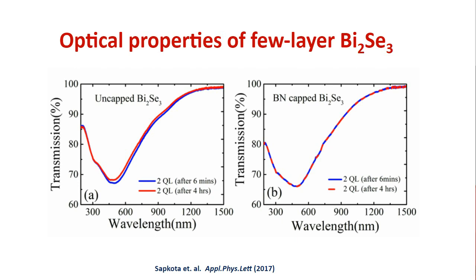In the capped sample, there is virtually no change, and that is exactly the result we wanted to see. That means if we analyze the capped sample, we would be sure there is no effect of surface oxidation. And so we proceeded to analyze both these capped and uncapped samples.